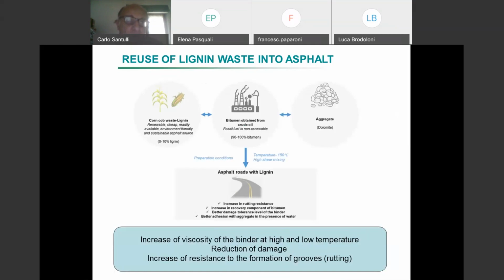The so-called freeze-thaw, you remember the freeze-thaw cycles. Asphalt has freeze-thaw cycles, and since it is also black, it absorbs heat very easily. What happens in practical terms is that it can go as low as -10 or -20 degrees in some cases, and it can go up to 70 or 80 degrees if the outside temperature is 35 or 40. That means these freeze-thaw cycles produce considerable deformation, and that deformation creates cracks.